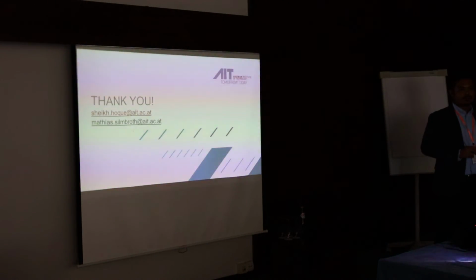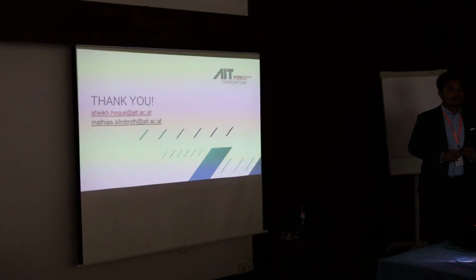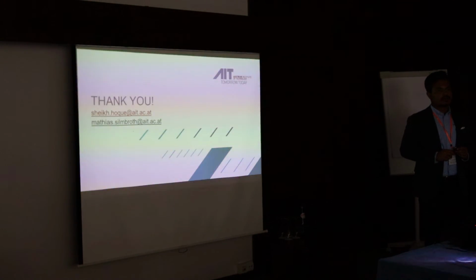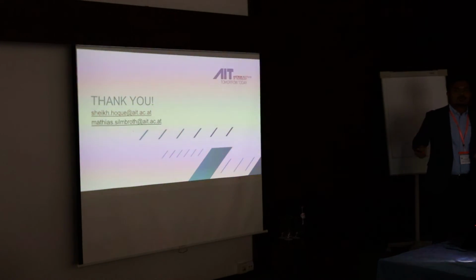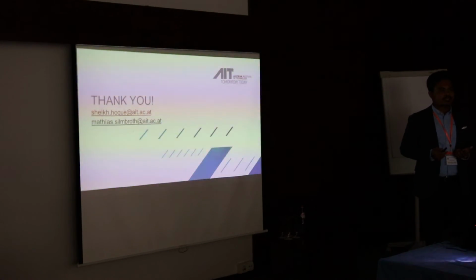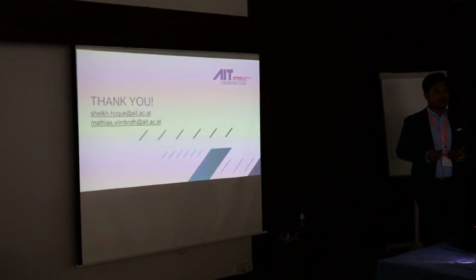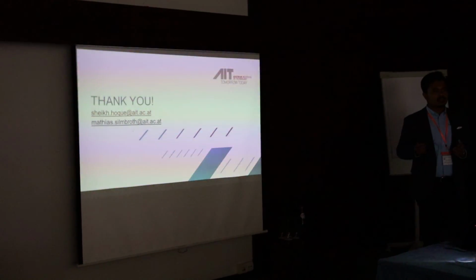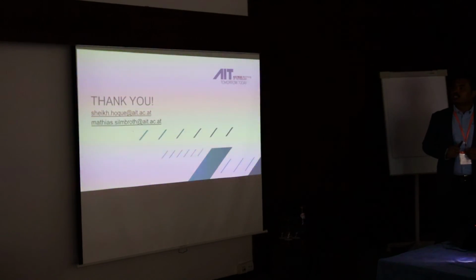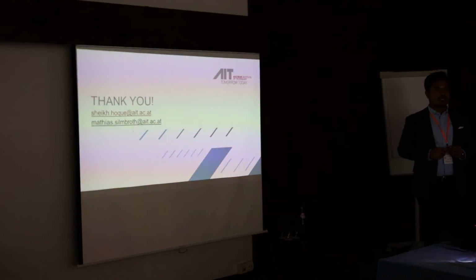Are there questions? Interesting presentation. I have a question about the applications. You mentioned, or maybe I did not get, what's the application for this kind of thin-walled WAAM part? It was a little bit optimistic, so they thought about a crash structure in a car, maybe a crash box. And what's the material? It's a commercially available alloy, aluminum 5183. You can buy it in wire form, and then we just manufacture with a wire arc additive manufacturing process.